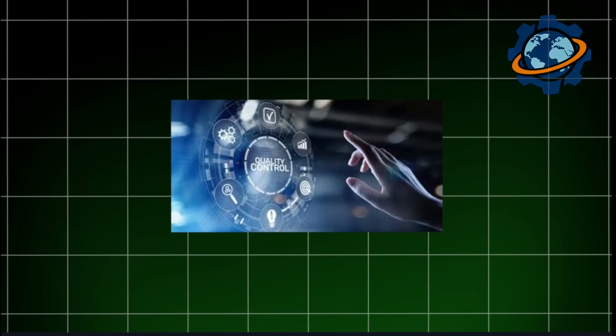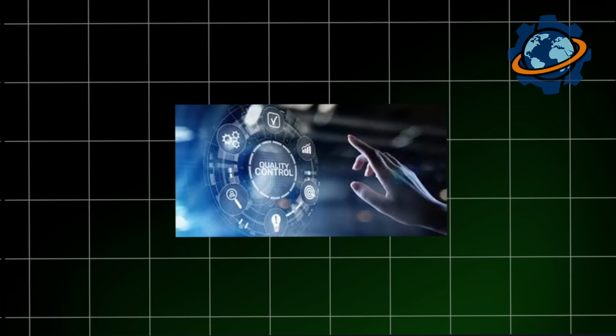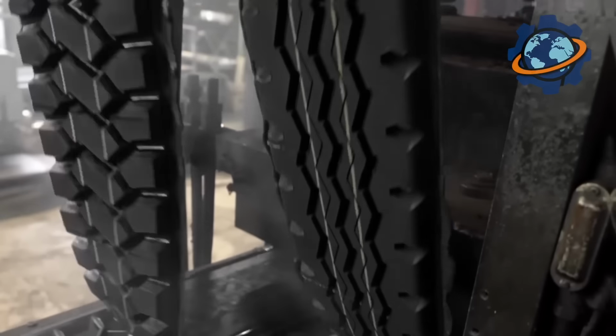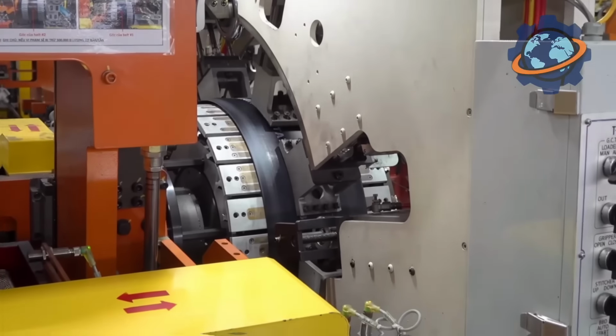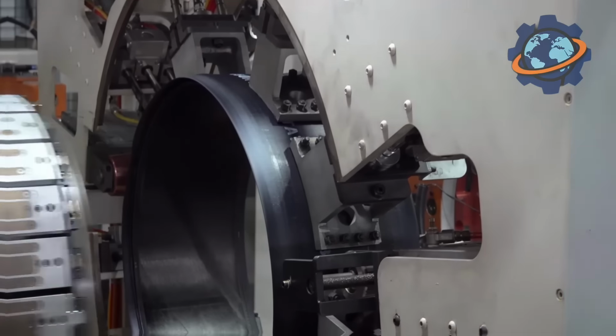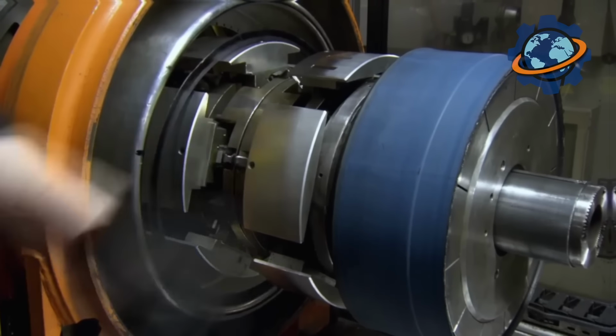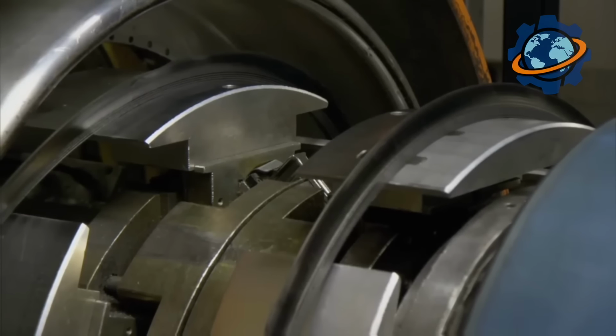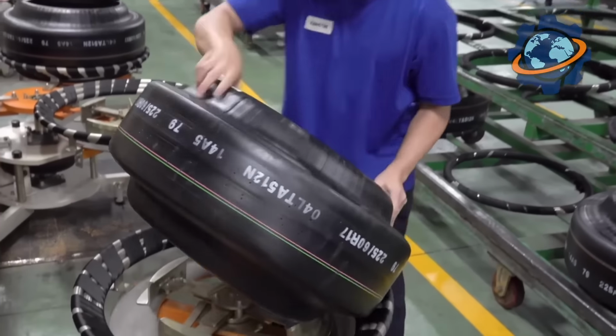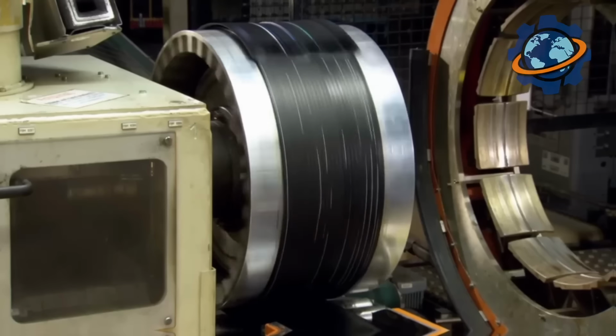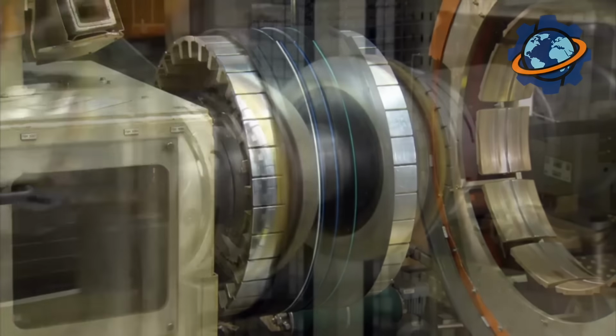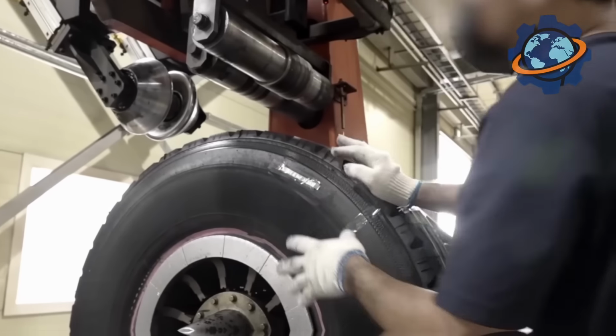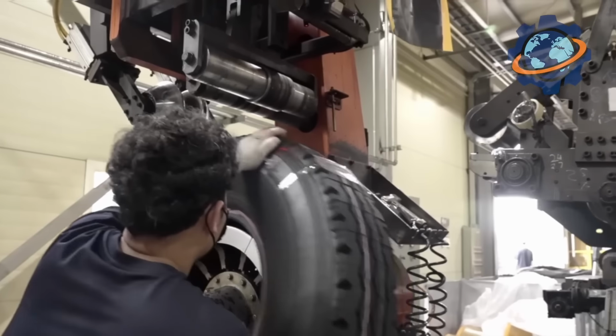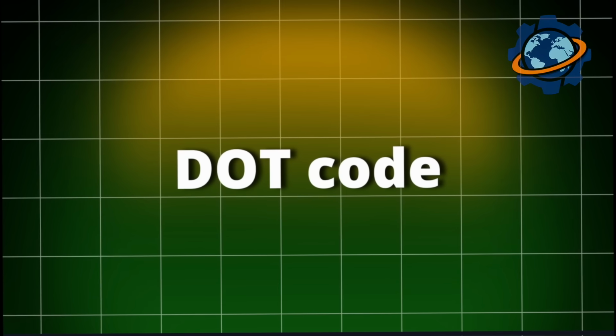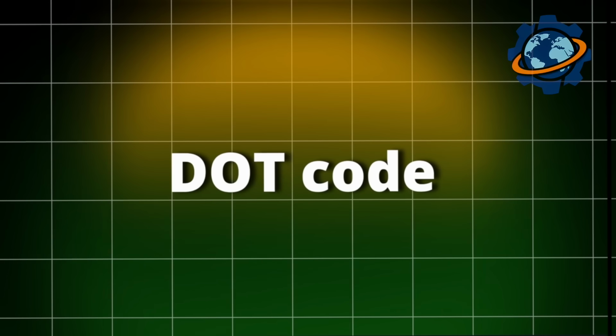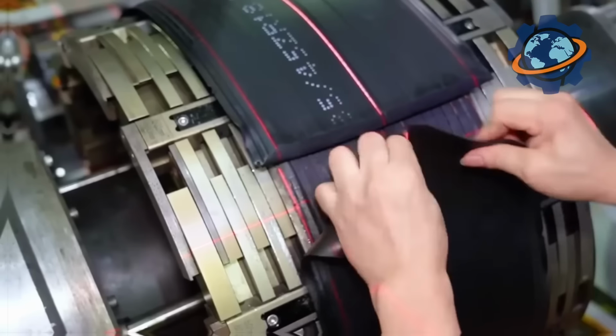After curing, quality control begins. X-ray machines scan internal structure, detecting steel belt misalignment, air pockets, or ply separations invisible externally. Uniformity machines spin tires at highway speeds, measuring force variations. Even 0.5-pound imbalance causes rejection. Tires must perform flawlessly at 120 miles per hour for tens of thousands of miles. Inspectors examine tread depth, sidewall finish, bead seating. DOT codes stamped into sidewalls identify manufacturing plant, date, batch number, critical for recalls.